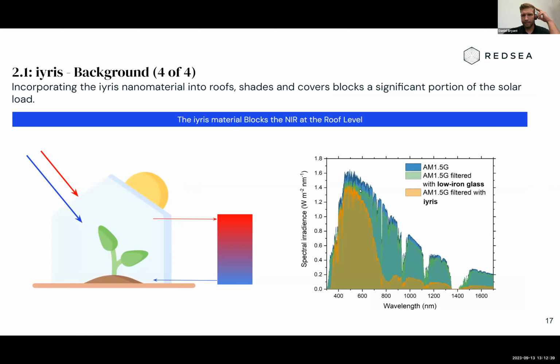You're talking about keeping your PAR as high as possible. There's a small penalty, but you're still at very high transmission. Then you drop down as fast as you can, and you keep your NIR low. And what you can start to do with this is tune where you drop off, and tune how much you're blocking.